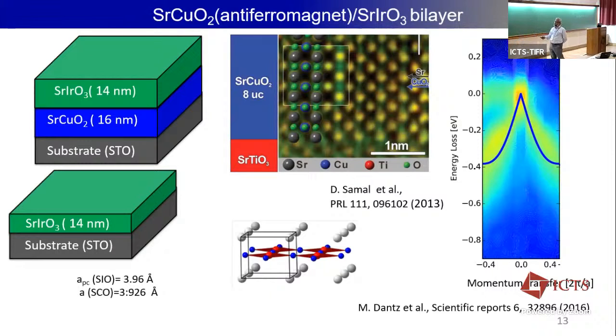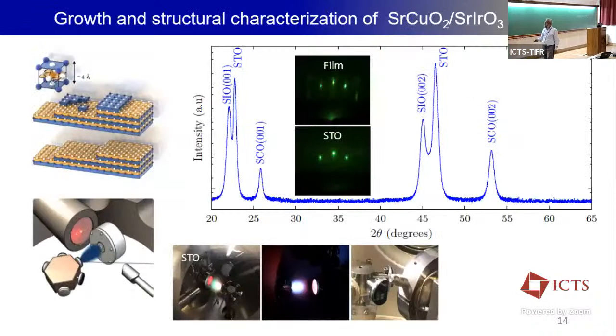This SrCuO2 was some of my earlier work, where it is an antiferromagnetic insulator, and we looked into its antiferromagnetism, because you cannot do any standard magnetic measurement. It's very difficult on thin films because it is an antiferromagnet. So you can do RIXS measurements, resonant inelastic X-ray scattering. You can look at the magnon dispersion, and this shows that this is really an antiferromagnet. So we looked into these two systems.